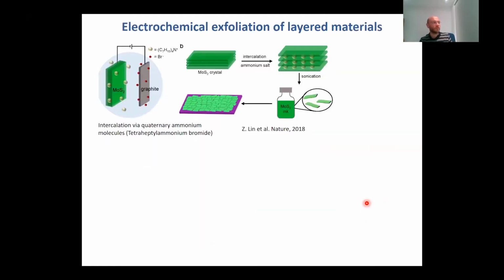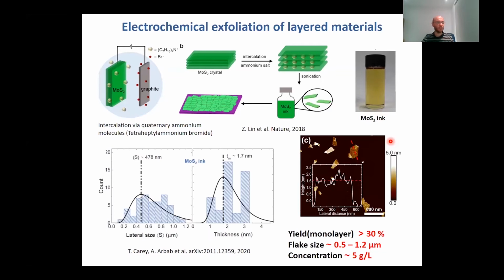So what we try to do here is use a recent electrochemical exfoliation process that uses, for example, an intercalation with quaternary ammonium molecules. In this case, it's tetraheptylammonium bromide. And actually, MoS2 crystals can be nicely exfoliated by intercalation, and then a mild sonication to get a large concentration of MoS2 inks that you can deposit on a substrate. So we follow this process and get highly concentrated MoS2 ink, which surprisingly gives much better flakes. In this case, we have flakes of really 1 nanometer, peaked at 1.7, so really, really few layers, which are also pretty large, half a micron roughly, but with peaks of even 1.2 microns. So that's exactly what we want to get more reliable features for printed devices.